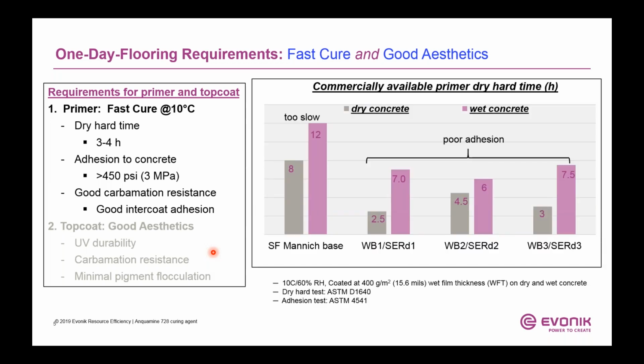So what are the available fast cure technologies in the market that could potentially meet the one-day flooring? We have looked into the solvent-free system and the waterborne system. These are all known fast cure commercially available systems that could potentially be used for primer. For the solvent-free system, mannich base is usually the typical go-to system for fast cure. And we evaluated all these systems on wet and dry concrete.